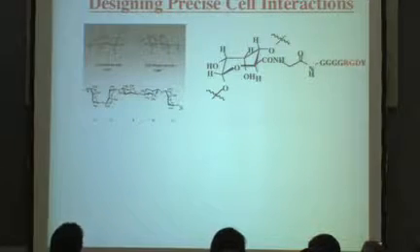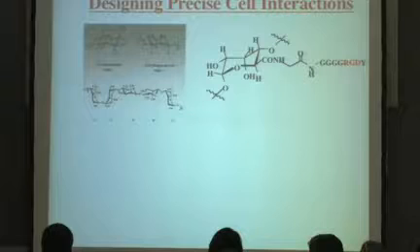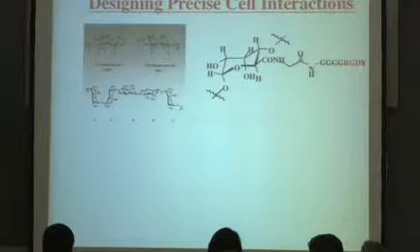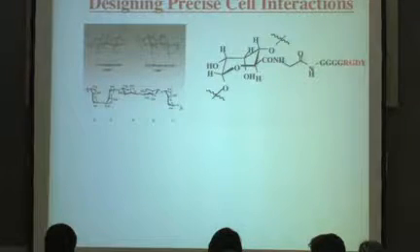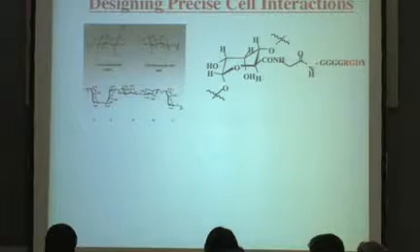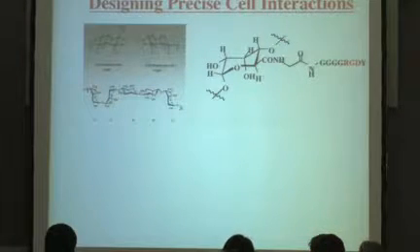And from a chemical perspective, if you go back to the work of many people in the past, Doug Lauffenburger and many others, obviously the adhesive interactions of cells with materials also are really important in controlling their migratory ability. So if we think about these polysaccharide-based materials that I described earlier for the protein delivery, they're actually not going to be very useful in and of themselves for what I'm describing now, because cells don't attach to them. So to get cells to attach and to be able to migrate, we couple small synthetic cell adhesion peptides, typically derived from fibronectin or other extracellular matrix molecules, as side chains.